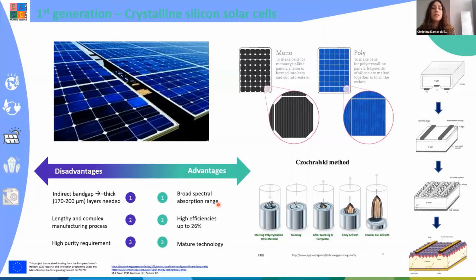Unfortunately, the band gap of silicon is indirect. So as we mentioned before, the absorption of a photon is less probable, and that's why we use thick silicon layers. The thickness is around 200 micrometers, and to give you an idea, imagine that our hair has a diameter of 2 micrometers. Also, the fabrication of crystalline silicon solar cells is a lengthy and complex procedure that demands high temperature, which quite increases the cost.